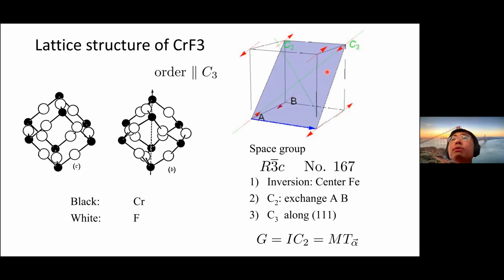The space group in that system is R3-bar-C, a trigonal space group. In particular, you have a threefold rotation axis along the 111 direction, a twofold axis which is in-plane and perpendicular to the 111 direction, and you also have an inversion center, which is the center of every ion. Basically, every atom here, every spin here, is an inversion center.